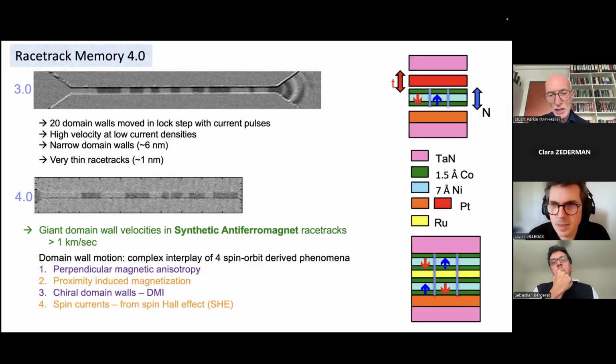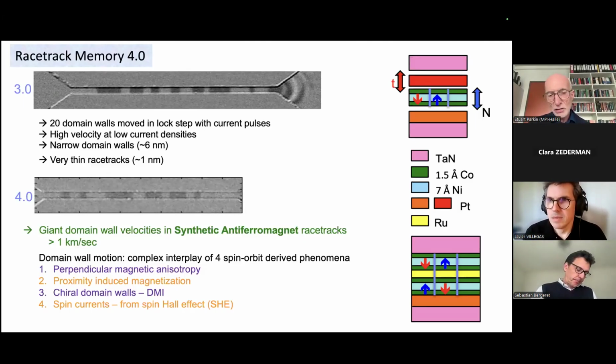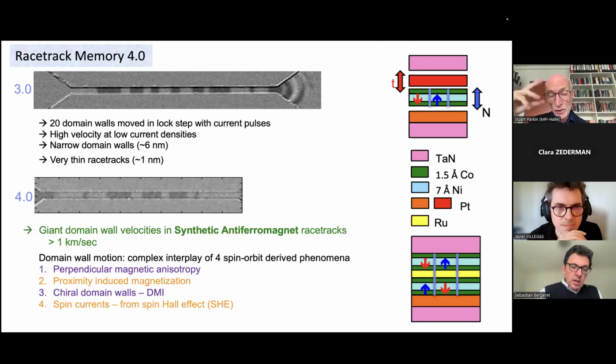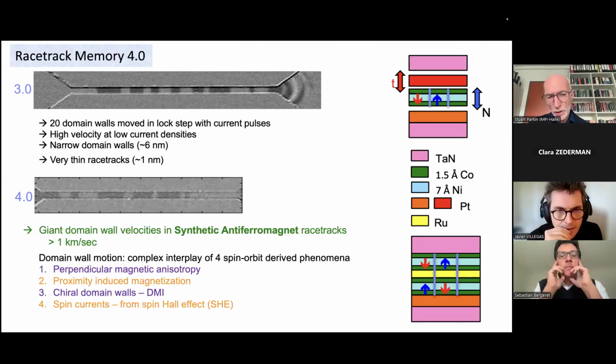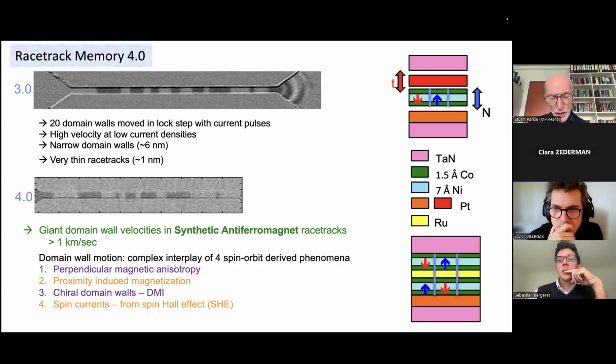4.0 is one of these synthetic antiferromagnets, and you can see there's much less contrast because effectively there's no net magnetization in this system, so the Kerr signal is much reduced. Nevertheless, we could demonstrate a series of domain walls moving backwards and forwards at speeds of about 1 kilometer per second. So the racetrack is a very interesting technology.